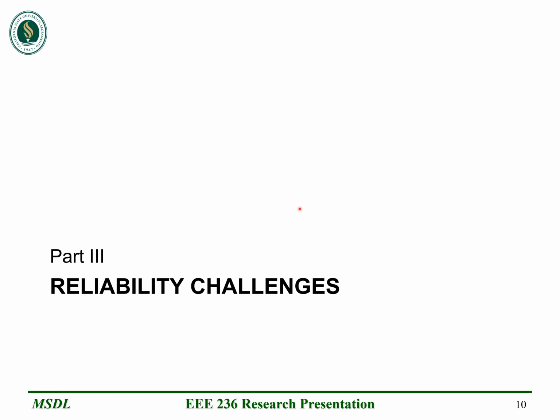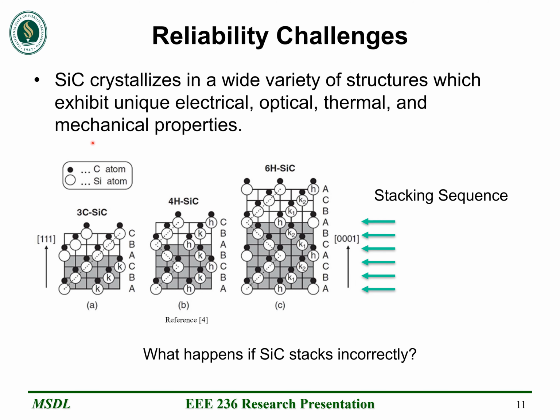So now we're going to look at some of the reliability challenges in silicon carbide technology. As we discussed previously, silicon carbide can crystallize in a wide variety of structures, and these can lead to different electrical, optical, thermal, and mechanical properties. So again, here is the same ball and stick model that we talked about previously with the different stacking sequences. You can see that in 3C, there's only 3 layers in the stacking sequence, and then that pattern repeats, and in 4H, there's only 4 layers and that pattern repeats, and so on and so forth. But what happens if the stacking sequence stacks incorrectly?